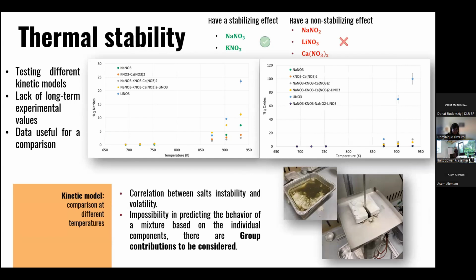So we are now working on this because, of course, these experimental campaigns in lab are very, very difficult to be carried out. But of course, we have a lack of long-term experimental values, but these data are very useful for a comparison. So we can state some correlation between salt instability and volatility, for example, and we can state which components can have a stabilizing effect, for example, sodium nitrate and potassium nitrate, or have a non-stabilizing effect, for example, the sodium nitrite, the lithium nitrate, and so on.